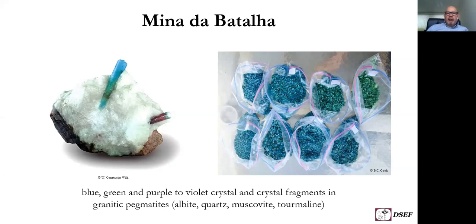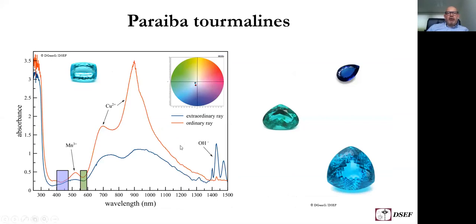Now, what is so special? These tourmalines, if we look at the absorption spectrum, are basically colored by the trace element copper. As you can see here, there are two copper bands. One is located here at around 750, and there's another one located in the infrared with a maximum at around 950 nanometers. And there's also manganese 3+, leaving behind transmission maxima in the blue and in the green, resulting in a bluish green stone, actually a turquoise colored bluish green stone.